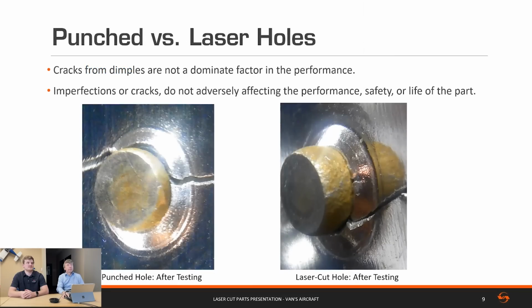As we compared this, we were also running samples of punched coupons. They developed fatigue cracking in effectively the same way. These components were not influenced. The mode of cracking or when it developed did not statistically change between the two components. Looking at the crack there in the picture, you can see that the crack did not progress again to the manufactured crack, but it cracked through the stress field.